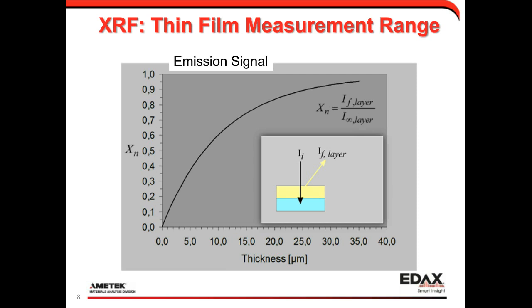When we're in a very thin regime, say on this scale, a couple of microns, you'll see that the signal ratio can change by, let's say, 20%, and you'll get a very small change in thickness. This is a relatively linear region of response, and this sort of determines the sensitivity for this particular measurement for very thin layers. And then you have the nonlinear region in between, maybe up to about 80% signal, where you can go from, say, 20 to 80%, and you have a certain nonlinear response of the signal. It's in this area here where you typically need some sort of a standard to calibrate the models.